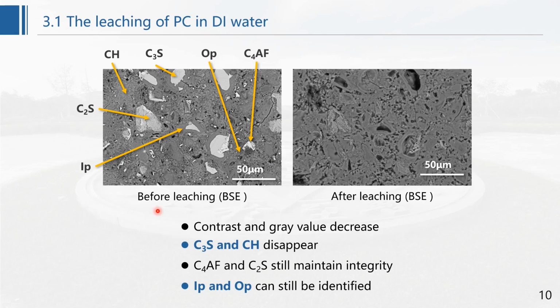Firstly, let's see the leaching of PC in deionized water. Here are the BSE images of the same area before and after leaching. You can see that after leaching, the contrast and the gray value of the matrix decrease.